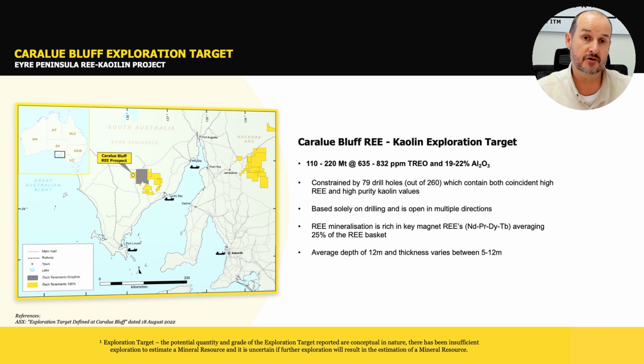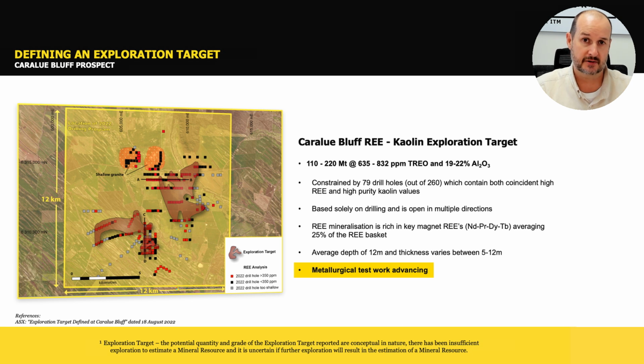So we know that the rare earths that are attached and hosted within those clays have quite an enrichment in the magnet rare earths. So they average about 25% of the rare earth composition in those clays. So it's well worth trying to crack that metallurgical code to get them out. So we have a very large area that we've identified these rare earth bearing kaolin clays over, and what we've done is restricted that exploration target to not where we've just got the rare earths, but where we have the rare earths and those white kaolin clays where they coincide.